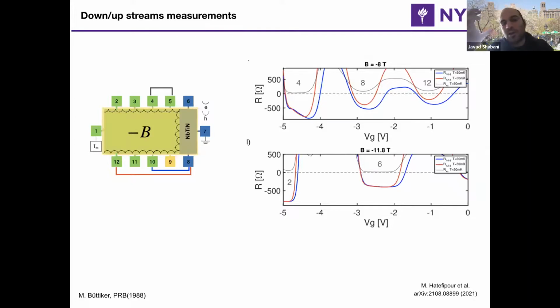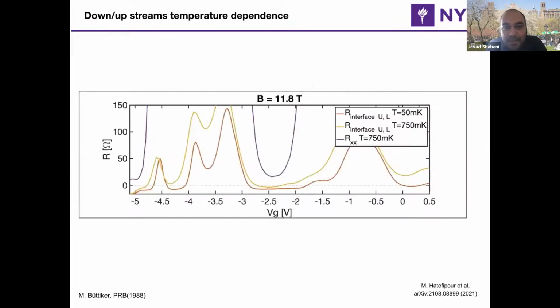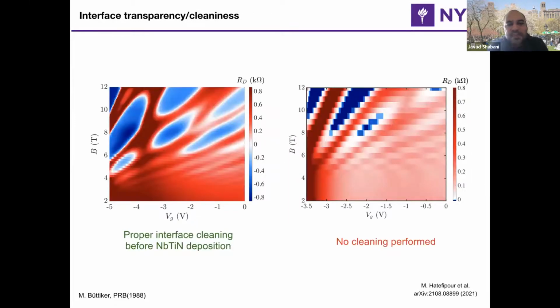So basically, if the quantum Hall is strong and you basically have the edge modes, the system just doesn't care. And more surprisingly to me, that value is kind of a set value, right? If you look at the 11.8 Tesla graph, at nu equals 6 and 2, both values are just following each other with high precision. You can also do temperature dependence, and as you would expect, once the RXX is lifted up, for example here at 750 millikelvin, the interface value also is lifted up. So if you compare the orange and yellow, yellow is the hotter trace, and you see the negative value is smaller, and you can plot it. There is really not much surprise there. It just follows the quantum Hall system. So we said, look, maybe this device is special or something. So we made different devices.